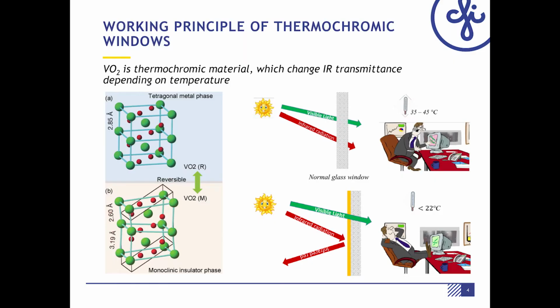Vanadium dioxide is usually used for inorganic thermochromic coating for smart windows. Vanadium dioxide has a phase transition at a temperature around 68 degrees Celsius. It switches from the semiconducting phase to the metallic phase. During the semiconducting phase, the vanadium dioxide coating is transparent for infrared light. If temperature rises, it switches itself to the metallic state and is able to reflect light.